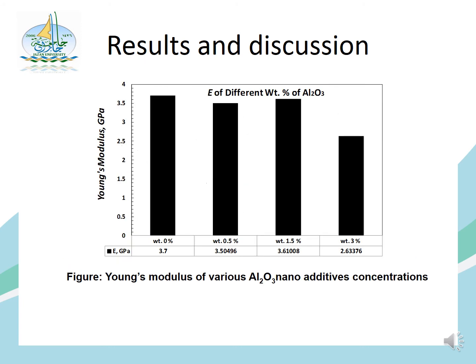Furthermore, on the second slide, we are trying to compute the modulus of elasticity E of the specimen, which can be estimated by using the value of the slope of the elastic region in the small punch test load displacement curve, as done in other studies. It follows the empirical correlation between the small punch test experimental result and E. There is an equation, one of the empirical equations that we extracted from one of our studies, and we correlate the factor computed by using the modulus of elasticity of the epoxy, which is around 3.7 gigapascal. We see here the value of the Young's modulus of the samples, and from figure B we can tell that the modulus of elasticity decreased by using the aluminum oxide nanoparticles.